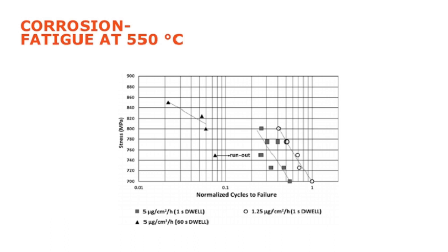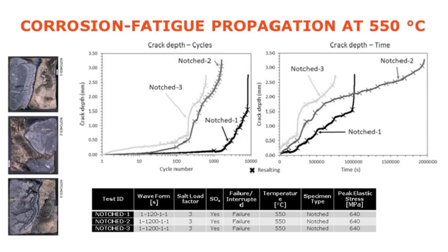Fairly simple story. And if we compare the two 1 second dwell tests, the square and the circle, again the square has a higher flux, so more corrosion than the circle, and we can see again that drop in fatigue life corresponding to that increased amount of corrosion. So that all makes sense. But again, this is quite a simplistic view, so we'll start to dig into a bit more what's going on, because I don't think SN curves are a great way to look at what's going on.